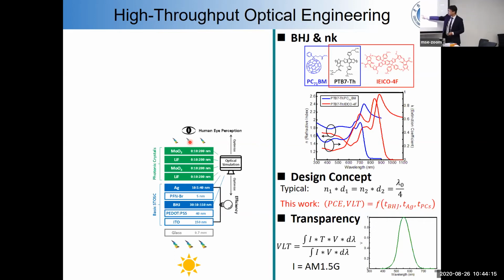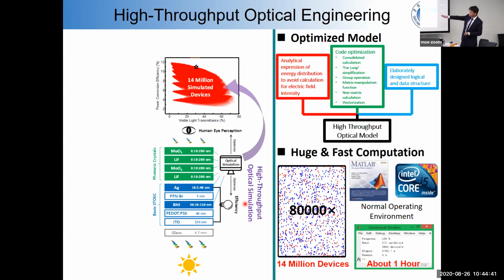So we can compute the power conversion efficiency and also the visible light transmittance as a function of the different thicknesses of the active layer, the thin silver electrode, and the photonic crystal, which means we are simultaneously tuning the thickness of this blue and green layer. Now that will be a huge combination. For just tuning these 6 layers, there are 14 million possible device architectures.